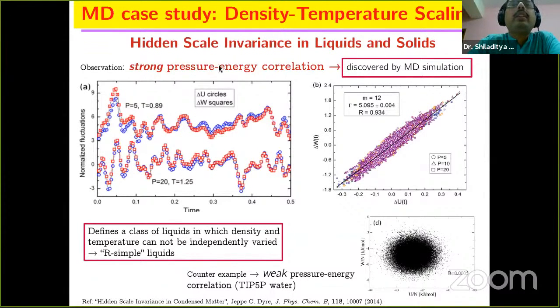Initially this was called a strong pressure-energy correlation, and you can quantify the strength of the correlation by doing a scatter plot of all these points, the pressure versus energy, and you can see that they are linear, and the correlation coefficient is 0.9. So the correlation is more than 90%, almost 93%. So this is a strong correlation between pressure and energy. This was the observation, and it was surprising because it was not expected. It just means that pressure and energy are not independent, and why should this be?